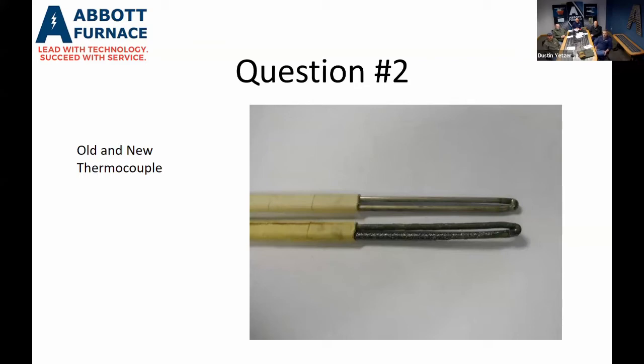If you run a furnace over 1700 degrees F, we recommend changing your type Ks out every 3 months because it starts to drift the temperature that the thermocouple gives to the instrument. On a 2050 furnace, that temperature usually is about a 30-degree drift in 3 months. If you're below 1700 degrees, you can get about a year out of a type K thermocouple without that 30-degree drift.